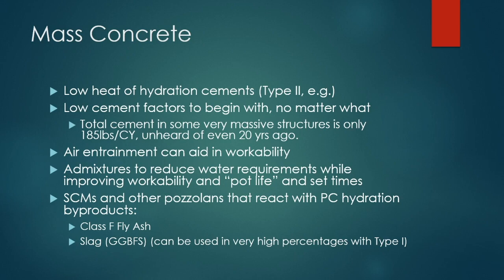They tend to be products that react with Portland cement hydration to become like a cementitious material. In other words, it actually takes the Portland cement hydration to kick off the reaction of something like a Class F fly ash or blast furnace slag.